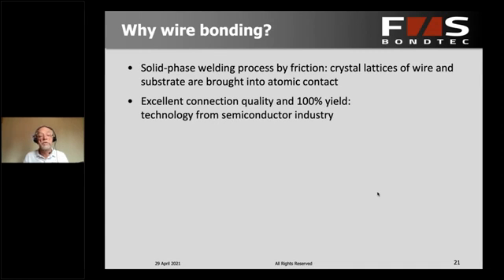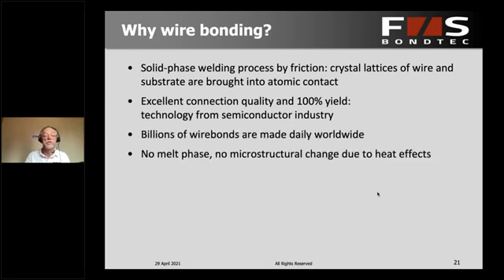The connection quality is really, really excellent, and typically we have a first pass yield of 100%. That's not so surprising because the technology really comes from the semiconductor industry, where extremely high quality and high yields are typically, in fact, just the basic requirement. Billions of wire bonds are made every day worldwide, so this is a huge industrial process that's very well understood. As I was saying, we have no molten phase, so we have no microstructural change inside because of heat effects, and that's a big advantage.